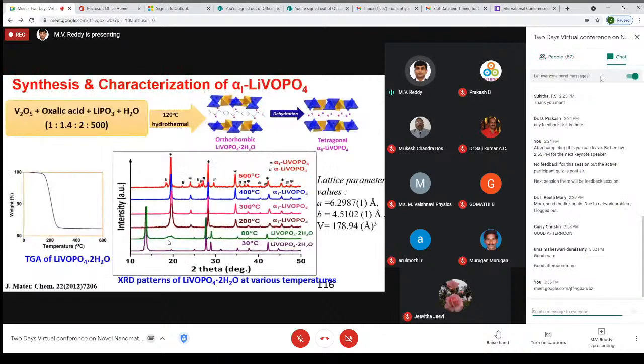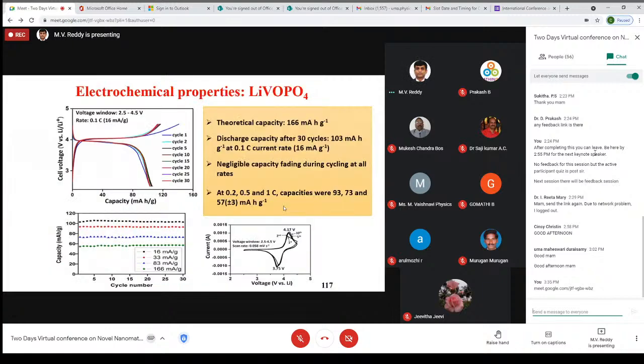So this is one example, the lithium vanadyl phosphate. This one we also prepared by a hydrothermal approach. Again, we have to decompose the water, so we have to heat the sample depending on temperature, and we can get different types of crystal structure. Interestingly, we again get nearly 4 volts, and we can see reversible peaks clearly from the cyclic voltammograms.